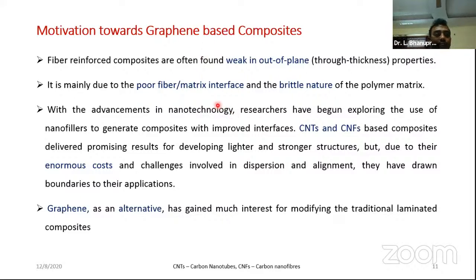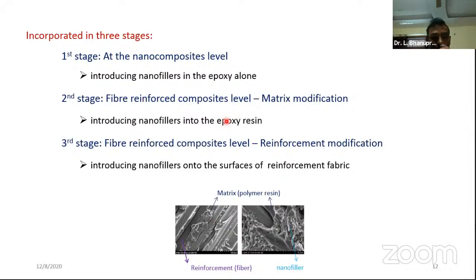Graphene has different derivatives: the pure graphene as well as the oxide form and the exfoliated form, and in each and every case I have explored. My work has been divided into three categories. First, I worked at the nanocomposite level, where nanofillers are directly introduced into the epoxy resin, and I studied the mechanical properties. From this work, I could know what concentrations of nanofiller I can add, what the maximum concentrations are, and what the optimum range of nanofillers is at which I can expect some improvement in the properties, or whether I notice any improvement or not.